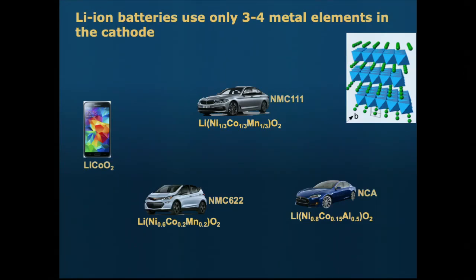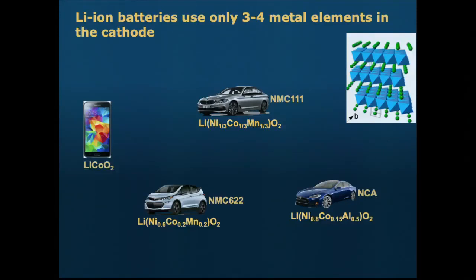But automotive technology uses substitution of cobalt, with nickel and manganese. It's essentially the same layered compounds that I showed you in the beginning. And they go by exotic names like NMC111, NMC622. That just stands for nickel, manganese, cobalt, and the ratio of elements is these numbers. So NMC622 means 60% nickel, 20% cobalt, 20% manganese. This is the staple of the EV industry today. If you buy a Chevy Bolt, it has 622 in it. I would say, besides Tesla, most of the market uses NMC622. If you have plug-in EVs like mine, that's more like NMC111, so it has a much higher cobalt content. If you're Tesla, you use something called NCA, which has aluminum instead of manganese, but it's still the same set of layered compounds.